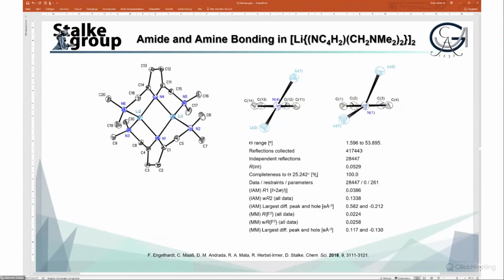Well, this is the sort of data crystallographers look at. We need high resolution data, almost 110 degrees in two theta. We need a hell of a lot of reflections. We need independent reflections. We need good R values for the comparison of reflections, and we need completeness. So there is no point in losing a cone of angles.